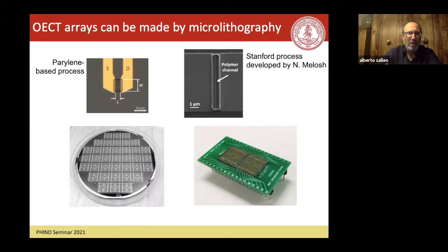One is what we call a parylene-based process, where you use a parylene film as a masking layer, and then we rip it off, and that defines all the features. Or we actually have a process developed by Nick Melosh at Stanford that uses all standard equipment in our clean room. This parylene process uses some equipment that is not standard. But the bottom line is that we can make arrays of these little sensors, and these look like electronic chips.